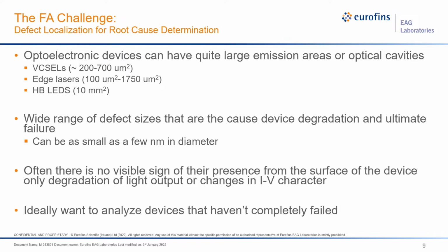So in trying to understand the failure, one of the biggest challenges you're going to face is locating the actual defect site, as optoelectronic devices can have quite large emission areas or optical cavities, and the defects can be as small as a few nanometers in diameter. Often there's no visible sign of their presence from the surface of the device, so only degradation of light output or changes in IV character provide evidence of their presence.